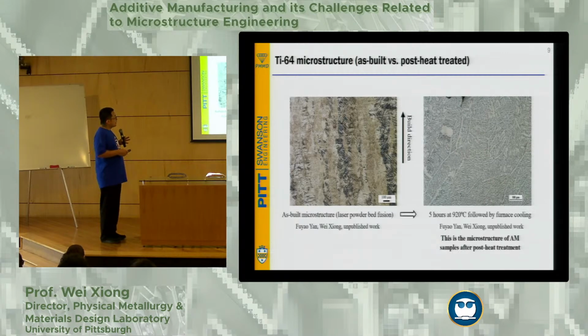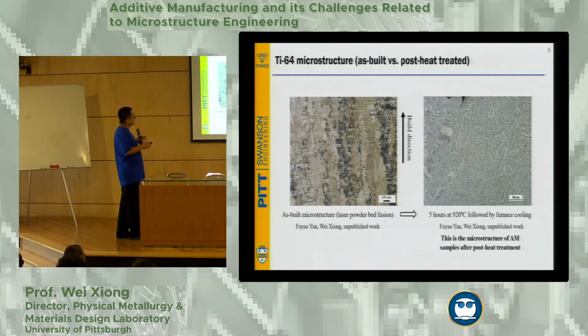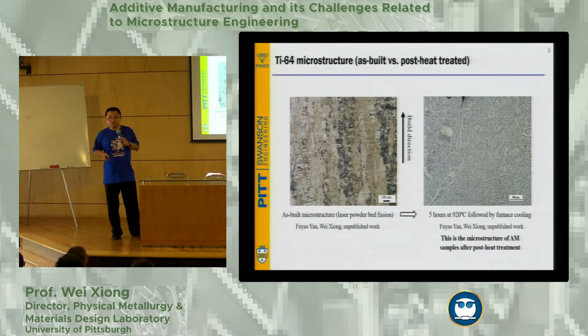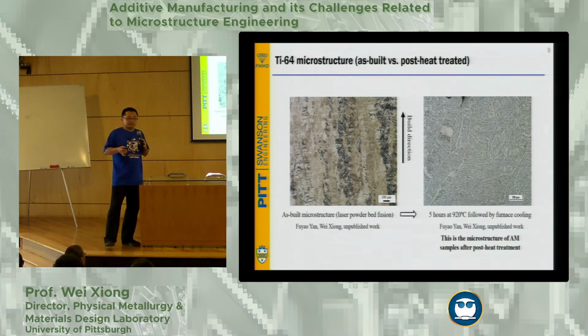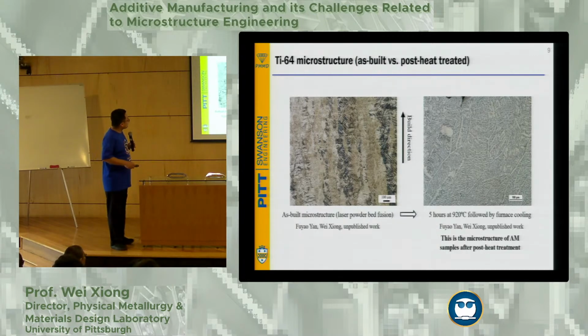And if you do further heat treatment, you'll see that some heat treatments can remove some of the texture. So that tells us, first, the as-printed microstructure is different. You have to customize a suitable heat treatment in order to engineer the microstructure and make sure you get desirable properties of the material.